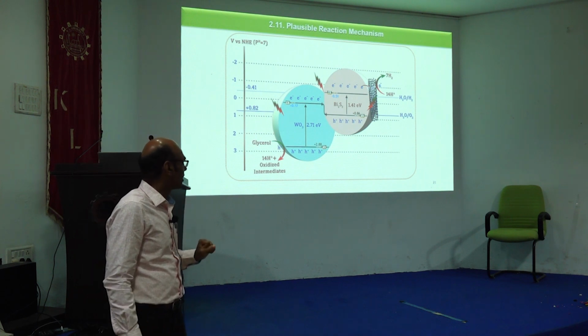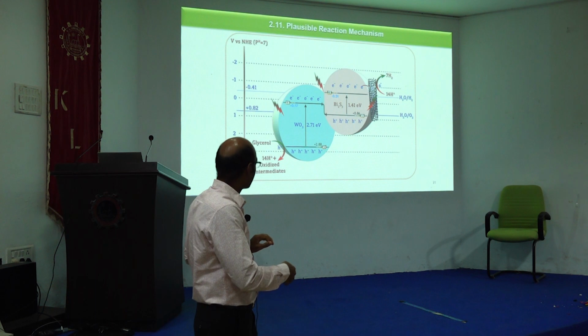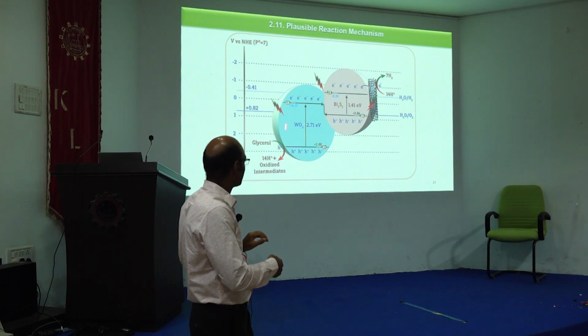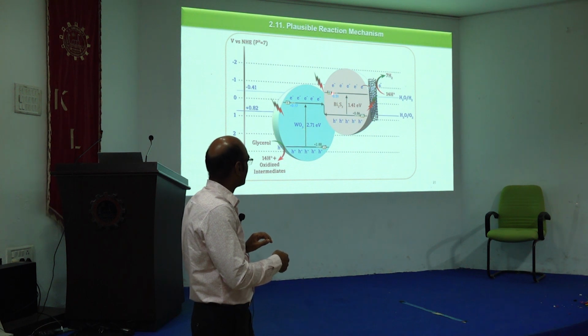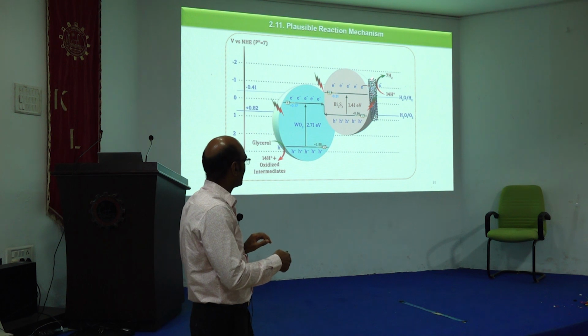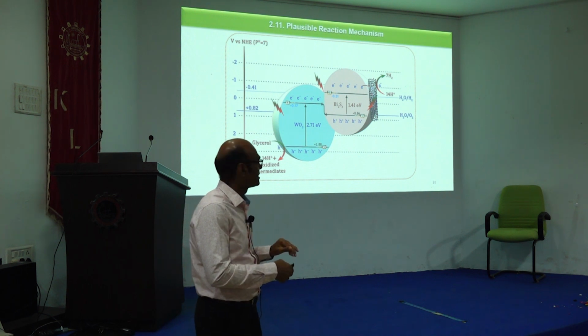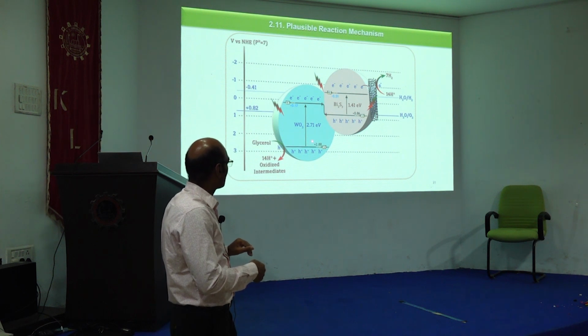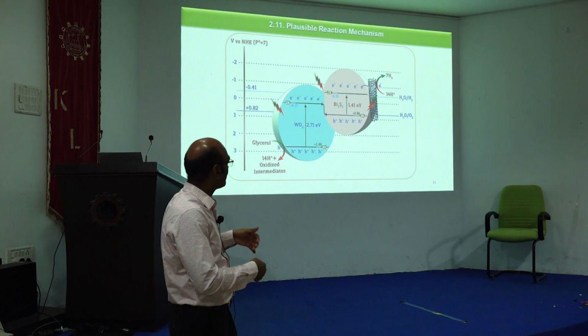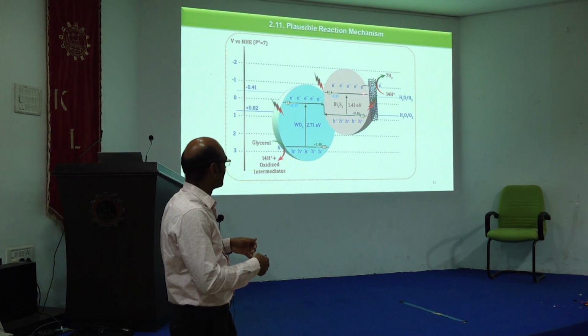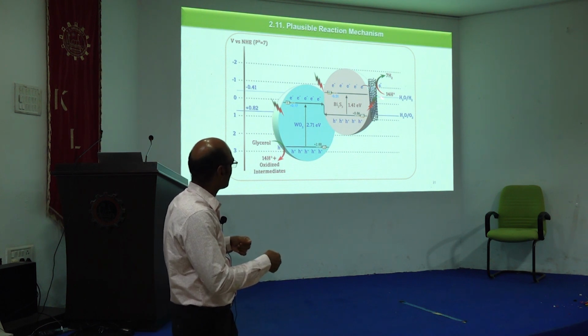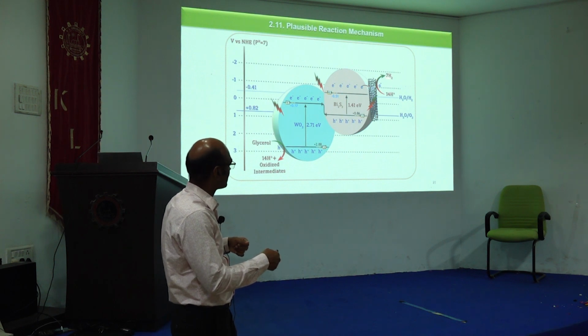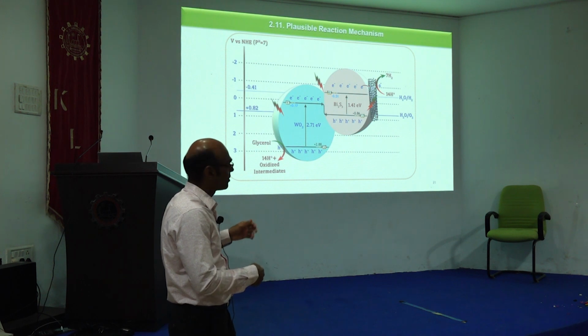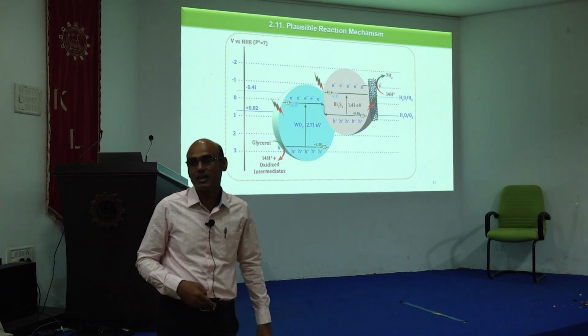From these results, what I explained here is that tungsten trioxide is the OEP material, that is, the oxygen evolution photocatalyst. Bismuth sulfide is the HEP, the hydrogen evolution photocatalyst, and the carbon nanotube works as a co-catalyst. Having a suitable interface, the photogenerated electron from the tungsten trioxide undergoes recombination with the bismuth sulfide valence band, whereas the conduction band electron from the bismuth sulfide is involved in hydrogen production, while this one is involved in proton generation. This proton is used here for hydrogen production. These 14 protons are involved in producing 7 H2 gas, as you can see. In addition to this, glycerol oxidation as well as water oxidation can take place to give similar hydrogen production.